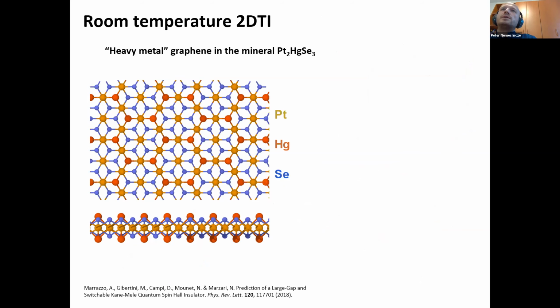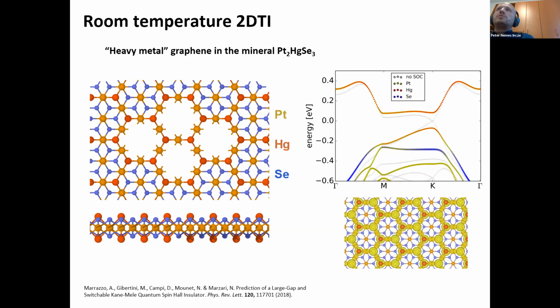Now, here enters our material, this platinum mercury selenide that I want to talk about. This was discovered by the group of Nicola Marzari in a paper that I show at the bottom, where they showed that it is a Kane-Mele insulator in the monolayer. This is because you can just disregard the selenium and platinum atoms that I've taken out, and the bands around the Fermi level are basically dominated by this honeycomb lattice of platinum and mercury that you can see here.